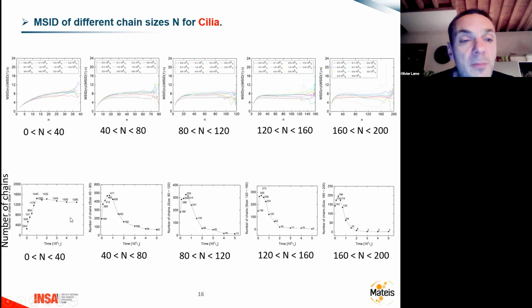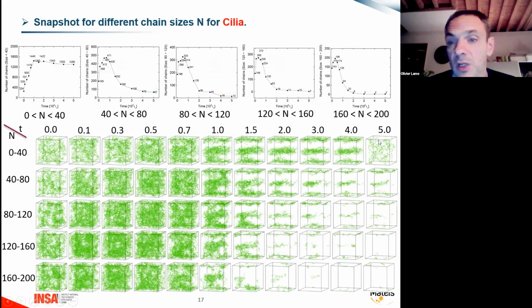Also here we have the statistics in terms of number of cilia, little cilia, and very big ones, and we see that there are a lot of little ones which stay constant, and for the longer ones, there are less and less, they decrease, and for the very long, there is a very small number of cilia. It means that most of the cilia are very short, in fact, which is very important for the mechanical properties, because if the pending chains are very short, it's difficult to transfer the stress. We have the localization of these different cilia, and as we can see, when the crystallization is finished at about 2.0, this is the time, they are located, of course, in between the lamella. It's quite logical.